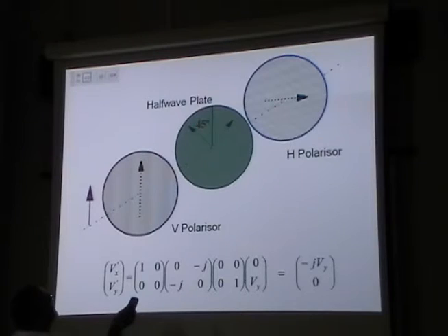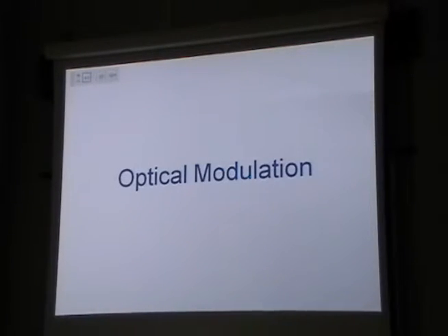If I rotate this so it's up, the axis is pointing in this direction, then I now have essentially cross polarizers again, so I have my black state. So all liquid crystals do in my head is they sit in this gap here and they manipulate the phase of the light in some way to either pass or block the light through cross polarizers. And that's why Jones matrices are so powerful. They have this really quite important fundamental property.